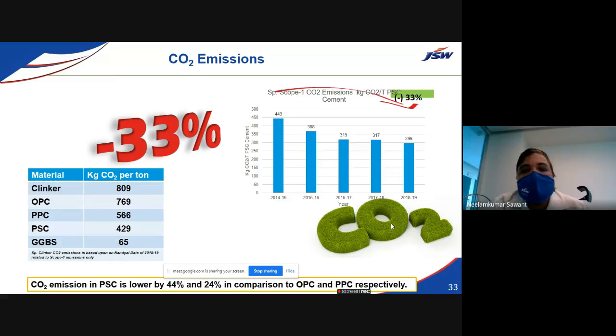We were previously having 443 kilograms of carbon dioxide produced for producing 1 ton of PSC. Nowadays it is about 296, so reduced by about 33%. We can have a comparative study over here. If the material is clinker or 100% OPC, for 100% OPC production, 769 kilograms of carbon dioxide is evolved in the environment. While producing the PPC, about 566 kilograms of carbon dioxide is evolved. And while producing PSC as well as GGBS, this is drastically reduced to about 429 to 65 kilograms.